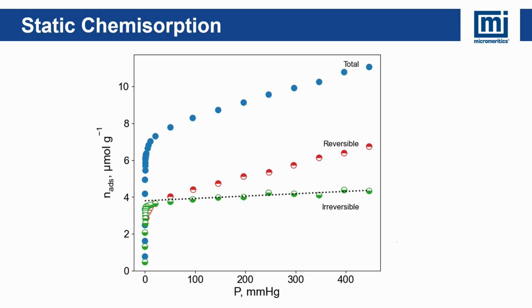The first step usually involves evacuating the sample while heating it. The sample is then activated at 400 Celsius with hydrogen gas for about 30 minutes, followed by an evacuation step. Afterward, the sample is cooled to the analysis temperature of 35 Celsius, at which point we can begin collecting the first CO isotherm. The first isotherm contains both strongly bound CO chemisorption and weakly bound CO physisorption.